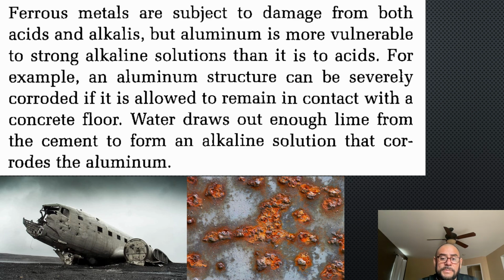Ferrous metals are subject to damage from both acids and alkalis, but aluminum is more vulnerable to strong alkaline solutions than it is to acids. For example, an aluminum structure can be severely corroded if it is allowed to remain in contact with a concrete floor. Water draws out enough lime from the cement to form an alkaline solution that corrodes the aluminum. So leaving parts on the ground is not a good idea.